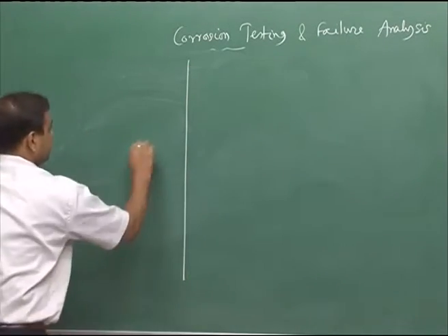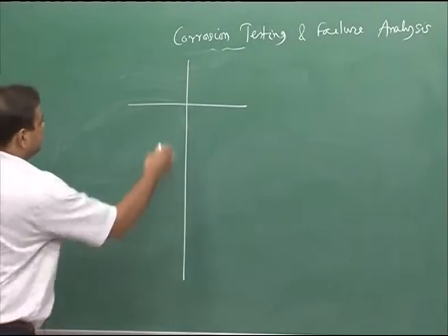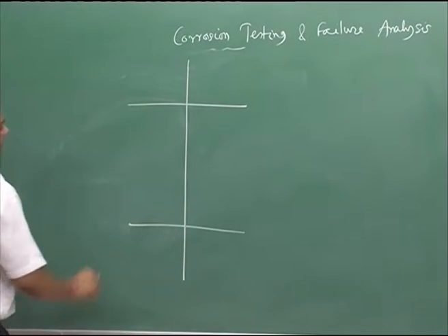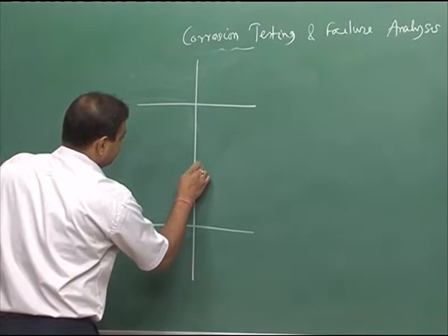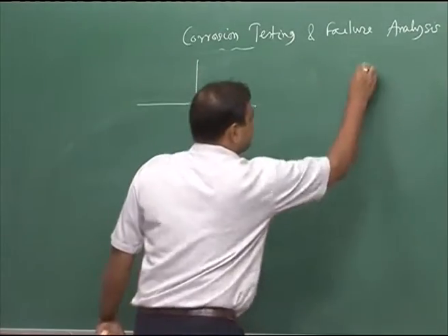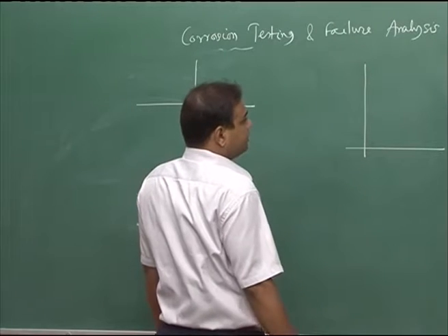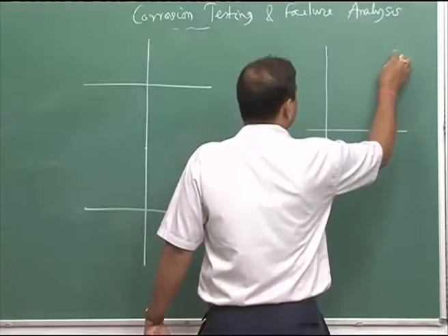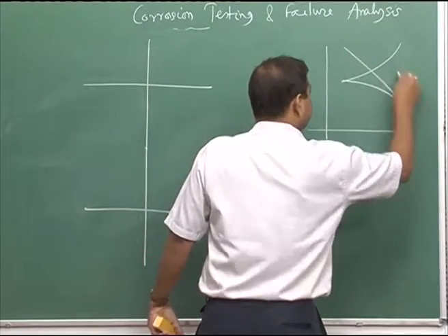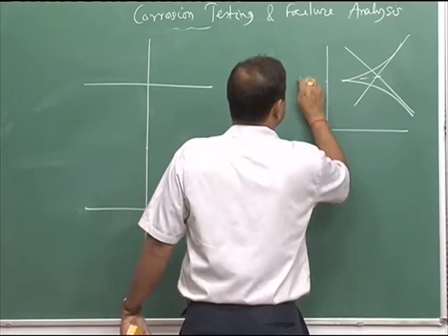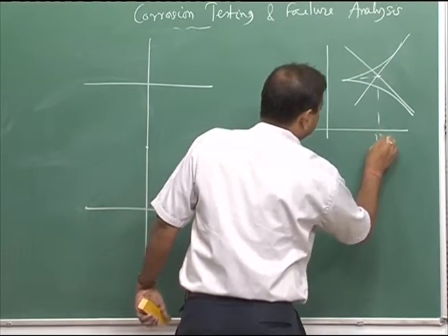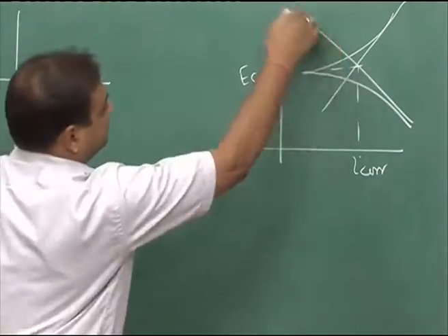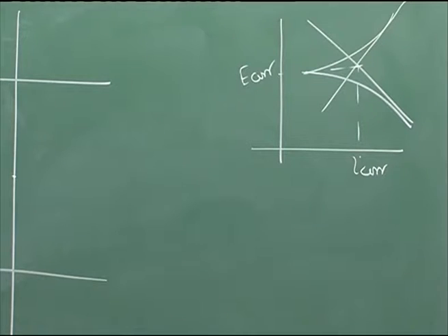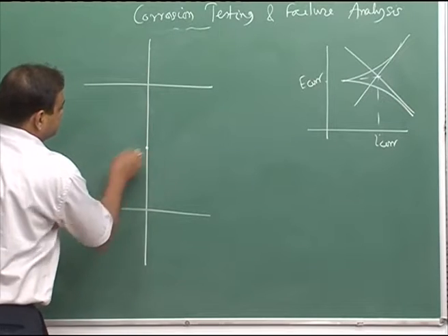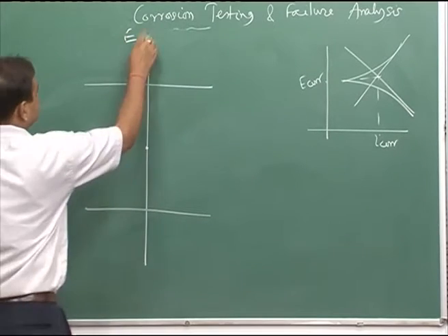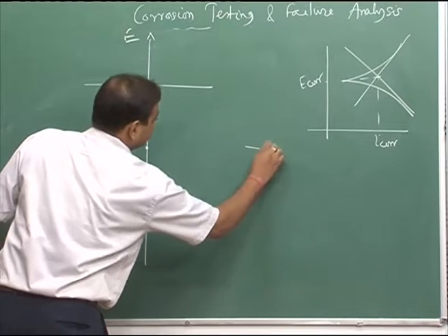So this is my cathodic side, this is my anodic side, and let us say my corrosion potential is this. If we compare the linear electrochemical polarization with Tafel extrapolation, we got a plot like this, with two linear parts. This is E corr and this is my I corr, this is my cathodic polarization, and this is my anodic polarization. So the same thing we would like to consider here. This is E corr, this is the potential axis, and this is my current axis.